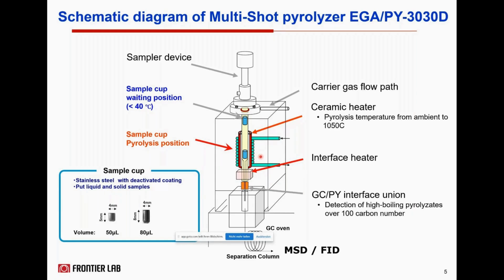And here the interface heating minimizes cold spots at the interface between the oven and the GC inlet. And this allows for detection of high boiling pyrolysates of carbon numbers even above C100. Here in the left corner, you see pictures of our sample cups, which are made of stainless steel, but inside they are deactivated by a quartz layer.